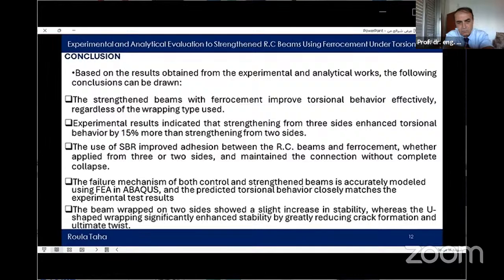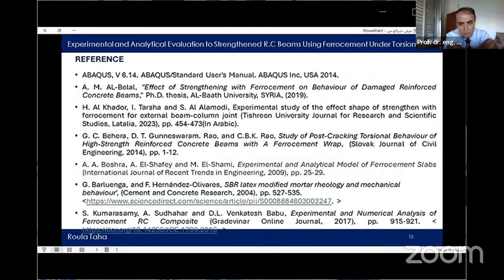The failure mechanism of control and strengthened beams is accurately modeled using finite element analysis by Abaqus, and the predicted torsion behavior is very close to that measured during experimental testing. While the beam wrapped on two sides led to a slight increase in stability, the U-shaped wrapping enhanced stability by notably reducing both crack formation and ultimate twist.